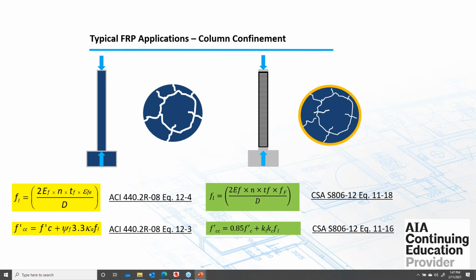Another thing a lot of the DOTs are doing, as I mentioned before, is just wrapping. Up in the north, where we're dropping snow and salt everywhere for the snow and ice, you get a lot of deteriorated columns from the plows going by and blasting them with all the snow and the salt. So you get a lot of spalling and cracking. The DOTs are using it just as a layer. They'll throw a layer or two of glass around the column, not really for any load carrying capacity, just to help hold it together and maybe extend the service life of the column a little bit longer.